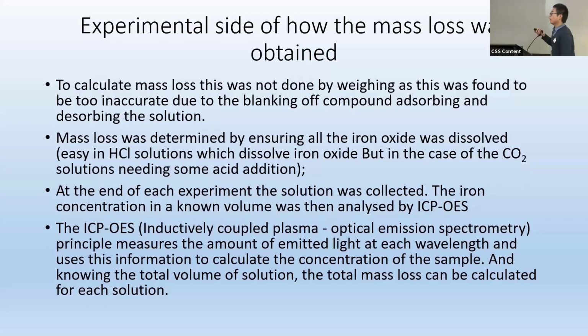It is important to dissolve the iron oxide or corrosion product in the solution, which is easier in the HCl solution, but you need to add a little bit more acid in a CO2 environment. At the end of the experiment, about 50 milliliters of the solution was collected and sent for ICP analysis. Then you have the concentration of the iron content in the solution, and with the known volume of the whole solution, you can calculate the mass loss for this particular experiment.